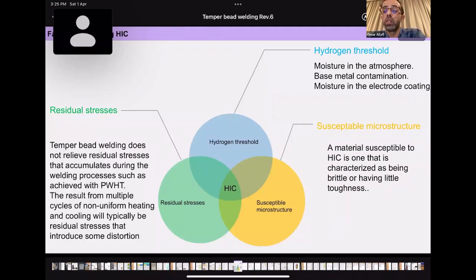Also, the residual stresses. So what I'm trying to say is that temper bead, the intent of this is not to relieve residual stresses, but to control mechanical properties. So the residual stresses after temper bead are always there. You have residual stresses, yes, less than normal welding, but you have residual stresses and susceptible microstructure. What I mean by susceptible microstructure is that HIC is characterized by being brittle or having little toughness. So the lower the toughness, the higher the chances for